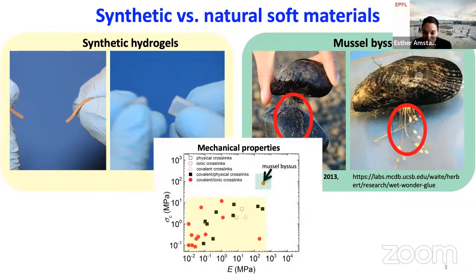And to put that a little bit more into numbers, I tried to summarize the stiffness of synthetic hydrogels that we can make, different types of hydrogels here plotted as Young's modulus versus the toughness, which I plotted as the tensile strength here. And you can see that we can vary these parameters over a wide range. They vary in composition and structures of these hydrogels, but we cannot get nearly to the same combination of stiffness and toughness that the mussel byssus, for example, displays. Similar things would be true, for example, for the cytoskeleton as well.